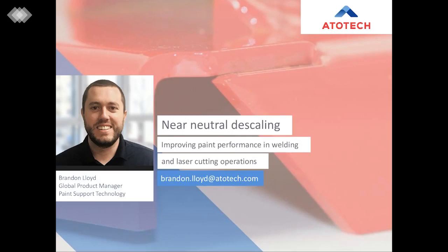Are these processes safe for use on galvanized steel? Yeah. As we saw in the presentation, where we talked about the iron and zinc etch rates, the etch rate on zinc surfaces is quite low, while they're still offering very good scale removal. In comparison testing with other proprietary chemistries, Uniprep AC has still had a significantly lower etch rate than some of the other chemistries that we have seen in the industry or evaluated.